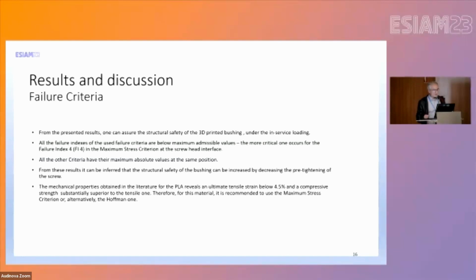The mechanical properties obtained in the literature for the PLA reveal an ultimate tensile strain below 4.5% and a compressive strength substantially superior to the tensile one. For this material, it is recommended to use the maximum stress criterion or alternatively the Hoffman one.